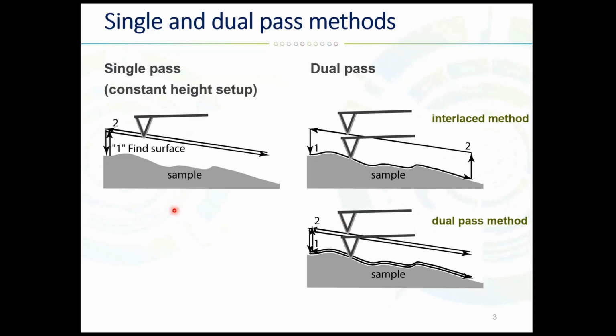So key thing in such measurements is to separate the short-range van der Waals forces from longer-range electrical and magnetic forces. So what we utilize is the so-called lifting mechanism that enables to probe the longer-range electrical and magnetic forces, and then it helps us to deconvolute them from the short-range van der Waals that are present during topographic images. So the height that we use to lift the tip over the sample is often a parameter that has to be optimized by the user in order to get the successful imaging. And usually varies from few nanometers to hundreds nanometers, depending on the range that you're interested in.